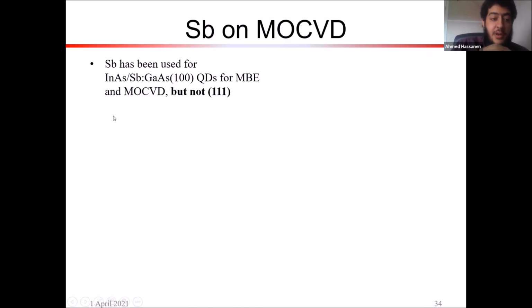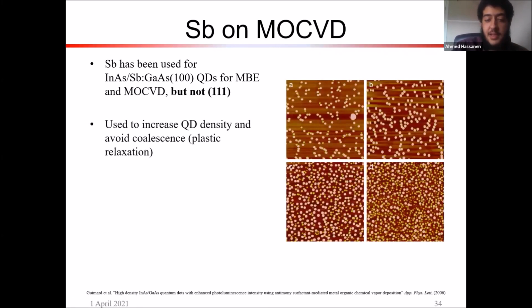Funnily enough, antimony has been used already, but on 100. So 100 indium arsenide on gallium arsenide already yields quantum dots, but antimony has been used to increase the density, and this creates smaller quantum dots. This decreases, for example, the probability of having a large quantum dot, which might plastically relax and create defects, which is not good. So you can see here, even on 100, antimony has an effect of creating a higher density of quantum dots. But it's never been used on 111.